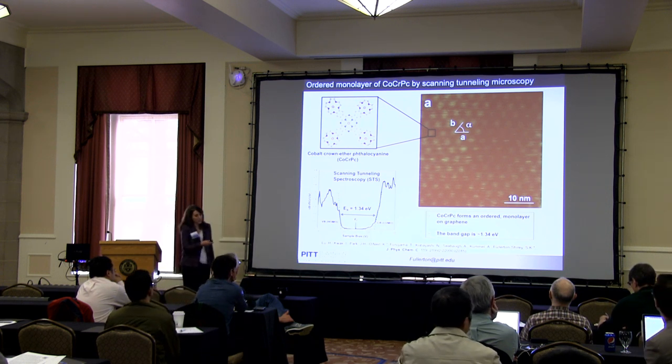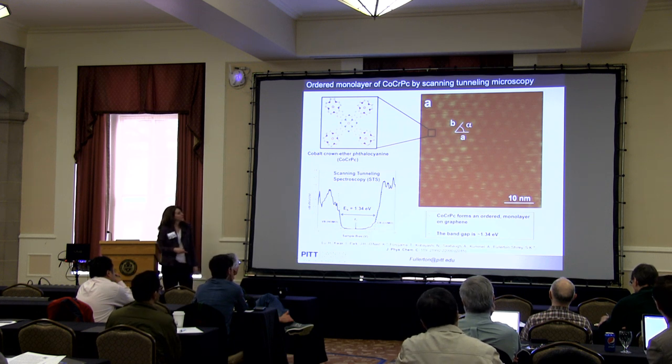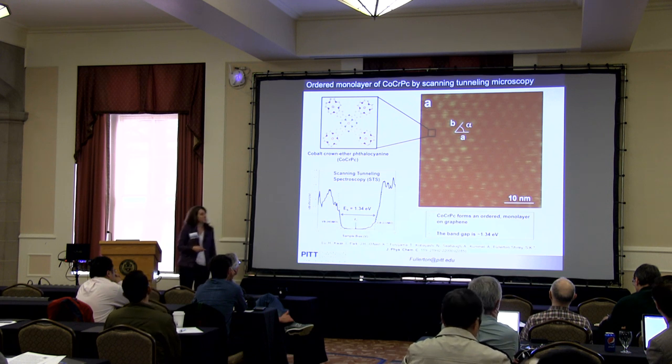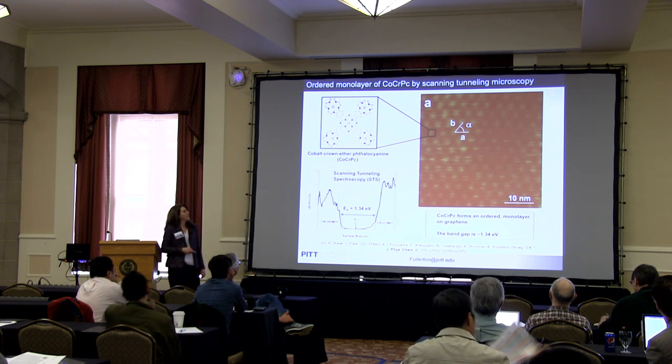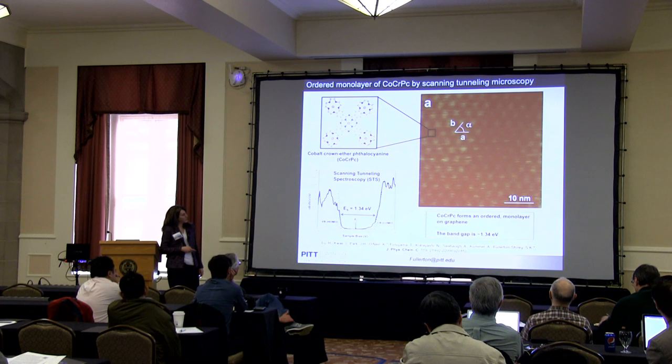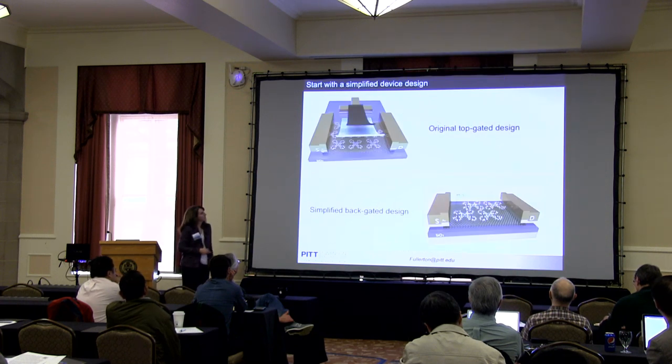We shouldn't be using graphene because it has no band gap, so the resistance range over which you could turn this thing off and on is really small. So I'm going to use MoS2, and he was able to get the same sort of bistability, as seen by this threshold voltage shift.